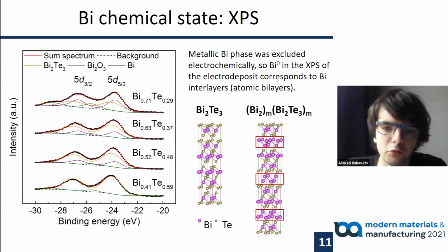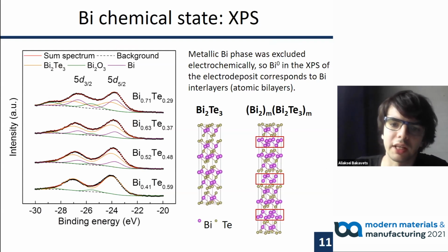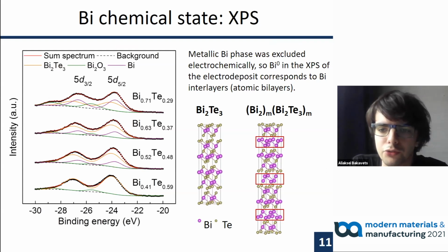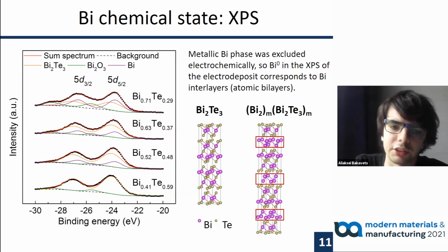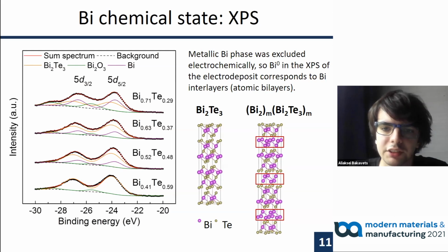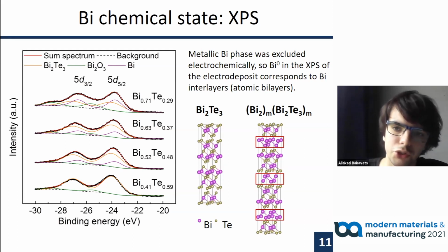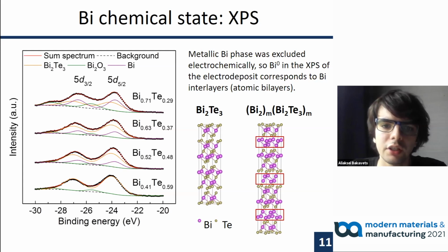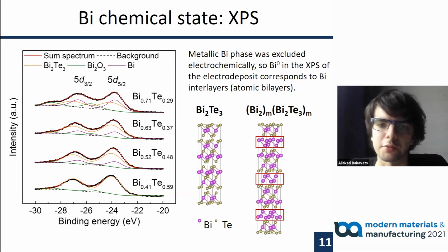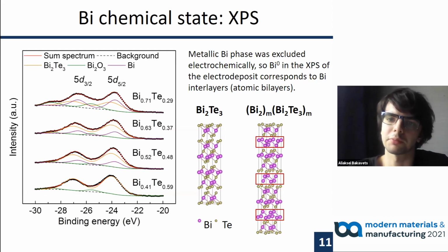One more evidence of bismuth bilayers formation was found from analysis of binding energies corresponding to 5d bismuth core levels in X-ray photoelectron spectroscopy. As we electrochemically obtained the superlattices deliberately in the potential region of metallic bismuth anodic oxidation, though below the potential of oxidation of bismuth interlayers, the observed contribution of bismuth in zero valence state in the X-ray photoelectron spectroscopy spectrum was a convenient indicator of the interlayers.